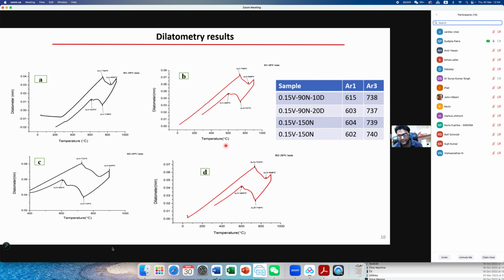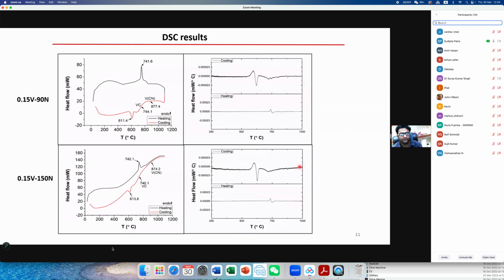So these dilatometry results suggest that Ar1 and Ar3 are around 615 and 730 for all the steels, similar Ar1 and Ar3, and for all the cooling rates. Now in the DSC result, we observed that during heating, there is only one change in the calorimetric value, around 741. Here is the phase transformation.